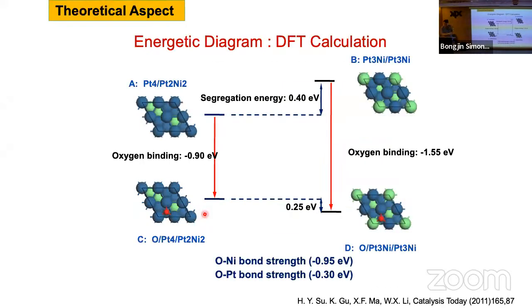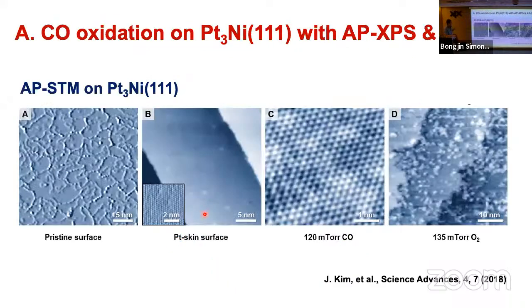So the bottom line is, I'm going to show you this one later, but the group from KAIST actually measured this approach, platinum-3 nickel. They bought this in a single crystal, and then they put the oxygen in, and they actually see how this platinum surface is behaving. Because what they did was they prepared the platinum, they put the oxygen in, in this case the CO, but also here's the oxygen in. When you introduce the oxygen, this is the clean surface, and this is the oxygen surface, about 135 mTorr, which is not a lot, which is not even ambient pressure.